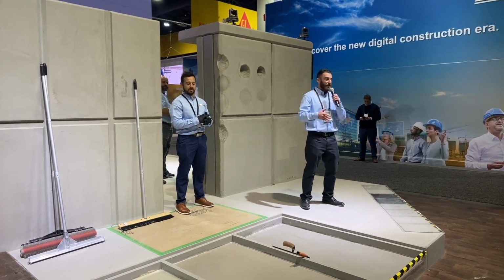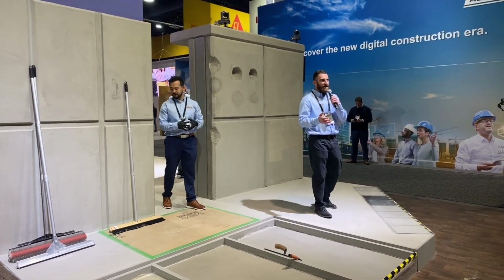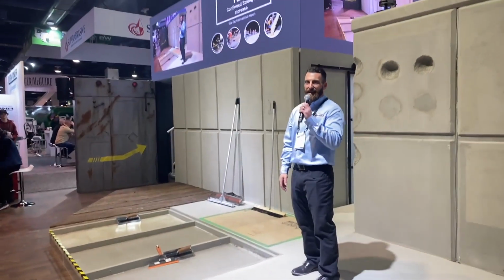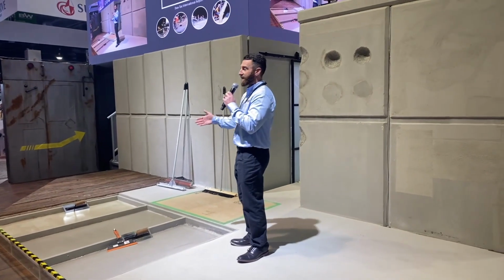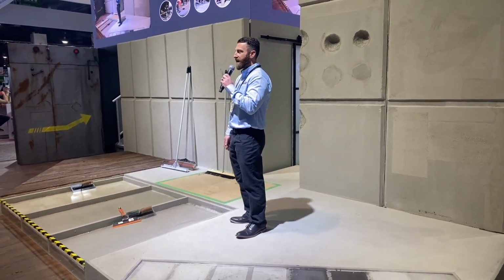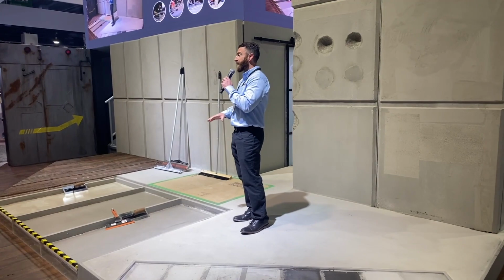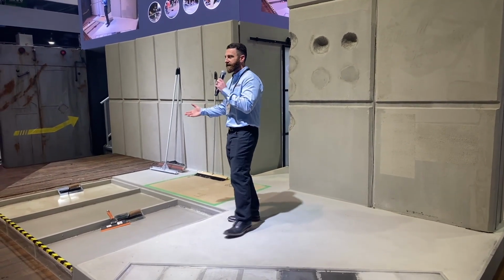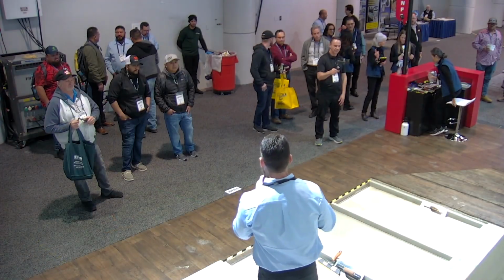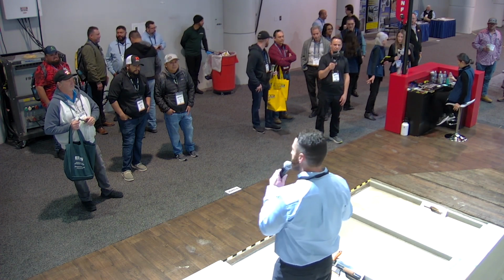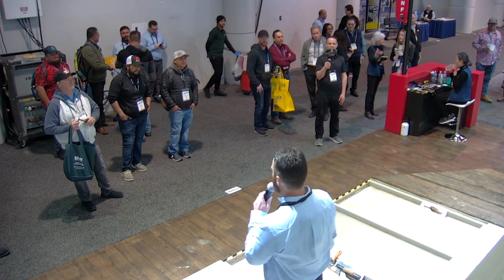Now, I mentioned durability. We actually placed Rapid Set cement concrete on SeaTac Airport back in the mid-90s. And we had independent labs come out and check the in-place concrete multiple times over the years. And they found not only does the compressive strength continue to increase well beyond 28 days, but the flexural strength today is actually double what it was when they first started landing planes on it back in the 90s.